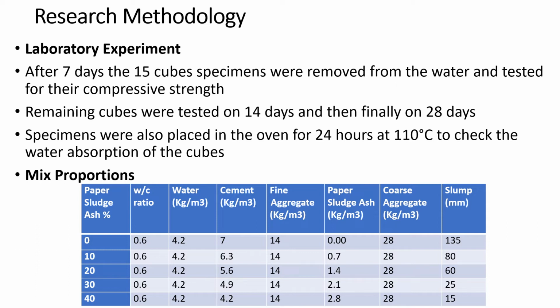And in the tables, you can see the mix proportion where you can see the ash percentage. The water cement ratio was the same for all the samples, and then you can see the cement, fine aggregate, the ash which we have used, the coarse aggregate, and we have also tested the slump values for that.